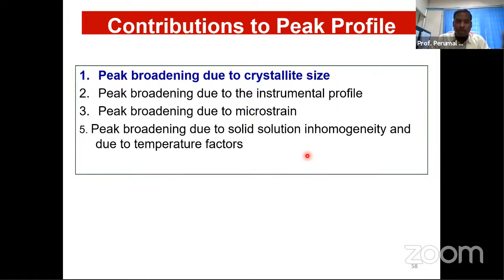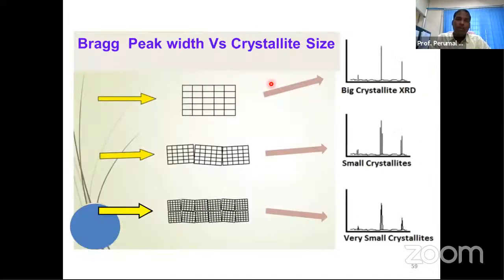And the peak broadening is also due to many other problems. Need not be only crystallite size and nano size. It may be an instrumental problem, or the crystal may have a defect. It may have a strain, twisting, twinning, we call it. Then you will get a broad peak. Or if it is a solid solution, cobalt, nickel, if you make an alloy, or silver and gold, if you make an alloy, if the alloy composition is not homogeneous, if there is inhomogeneity, then some peaks may be broad. That should not be taken as crystallite size or nanoparticle broadening. Only the broadening due to crystallite size is the characteristic for nano size.